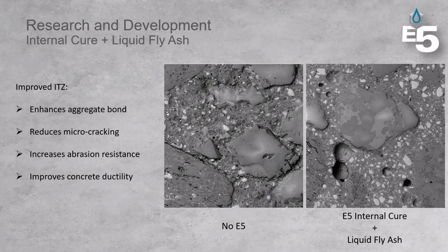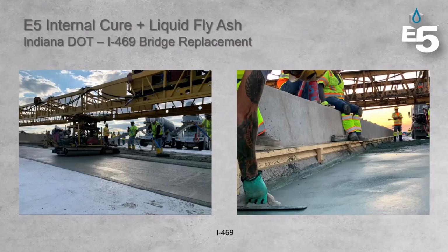It makes sense that that aggregate would not be holding. When you improve the ITZ, you do a lot beyond enhancing the aggregate bond, right? You improve abrasion resistance, right? You improve concrete ductility, and you reduce micro cracking. Those cracks you see that are macro cracks, micro cracks, they're nano cracks when they start. They're much smaller than that before you can even see them with water.